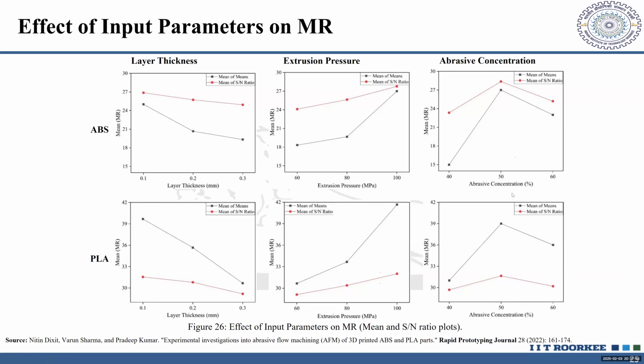So what you see is that the material removal rate is increasing till 50%, but after you increase it from 50 to 60%, the material removal rate is not increasing that much. The reason for that is that there may be certain kinds of collisions among the abrasives, as a result of which the material removal rate would be less. So it is not so that only 100% loaded abrasive media will give you the desired surface finish. You can have the loading of the abrasive media even less than 50%.